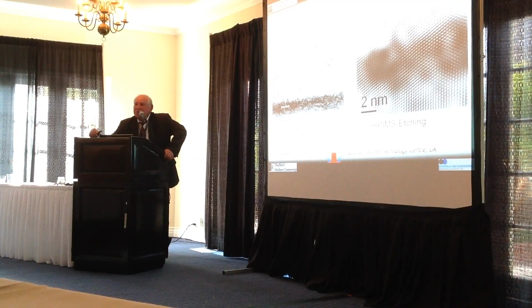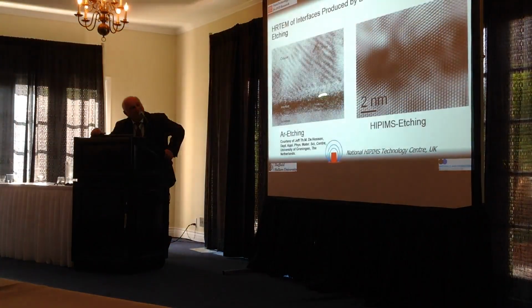Now, you can clearly see the benefits of using metal ion etching by HiPIMS. If this is your substrate, this is your coating, and if you analyze the chemical composition of the interface after being bombarded with chromium ions, you find that you can implant this species deep into the substrate. And this has huge implications on the crystallographic structure of the interface. This is an interface which is prepared by argon etching. It's almost amorphized, it is highly disordered. And this is the structure of the interface after HiPIMS etching.